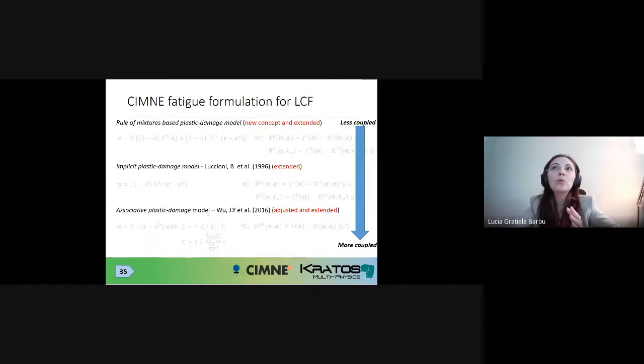Basically, because I want to show to you there is a transition between a less coupled behavior to a more coupled behavior. What do I mean with less coupled behavior? For instance, the rule of mixture-based plastic damage model can allow two different surfaces, one for plasticity and one for damage, which behave in a completely different way. The implicit plastic damage model by Viviana allows two different surfaces, but if they are moving in two different ways, you're losing convergence, you have instability in this model. This is a big limitation for this model. Now, the associative plastic damage model proposed by Wu and Cervera only has one yield surface, which is common for both plasticity and damage together.